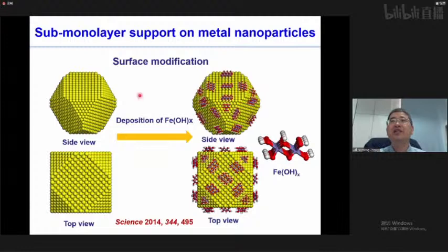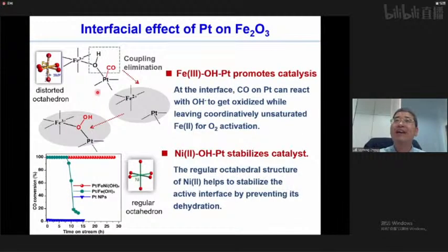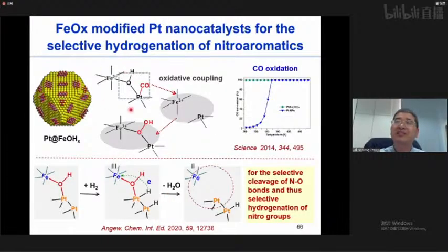So another approach is to introduce a metal inorganic interface. Several years ago, we demonstrated that if we deposit iron hydroxides on Pt, then we create a really interesting interfacial site, which can do the coupling elimination of carbon monoxide. So in this case, basically, the interfacial hydroxide can react with carbon monoxide, which is a reducing agent. So with this understanding, we found that it's also possible to use this interface for the selective hydrogenation of these nitroaromatics.